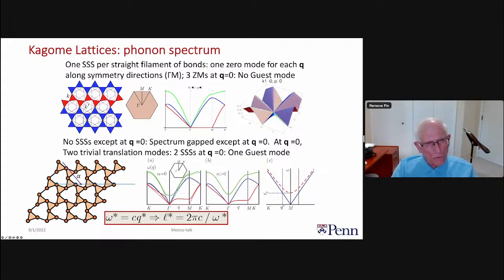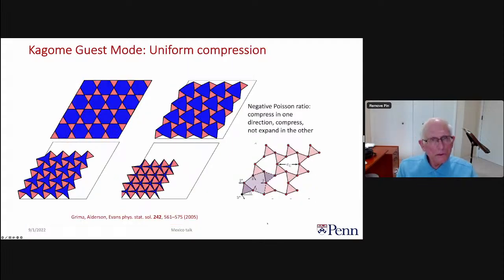So as I change alpha, I don't change the qualitative features of the band structure. That means that we have a topological class which is robust as I compress the system like this. And we have the zero modes in this behavior right here at the edge. This incidentally defines a length scale for you. Q star is the point at which this curves over, and you can create an omega there where C is the sound velocity. Now this is the full guest mode I was telling you about. You can go all the way down to this, and we will have something more to say about this later.